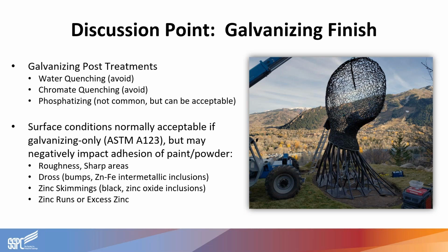And some of these post-treatments are going to alter the surface chemistry. They're going to passivate the coating. Phosphatizing, or a zinc phosphate quench solution, will passivate the surface, but also produce a surface that is acceptable for painting. While others, like the chromate quench or the water quenching, will leave us with a surface that is difficult to top coat. Although water quenching does not change the surface, a water quench bath typically contains contaminants that will be deposited on the surface and will interfere with paint adhesion that are difficult to see.